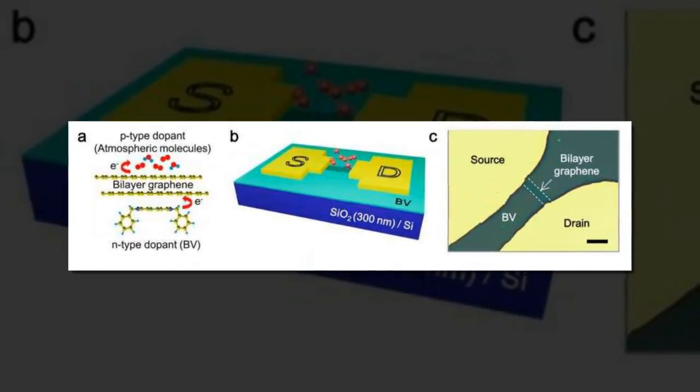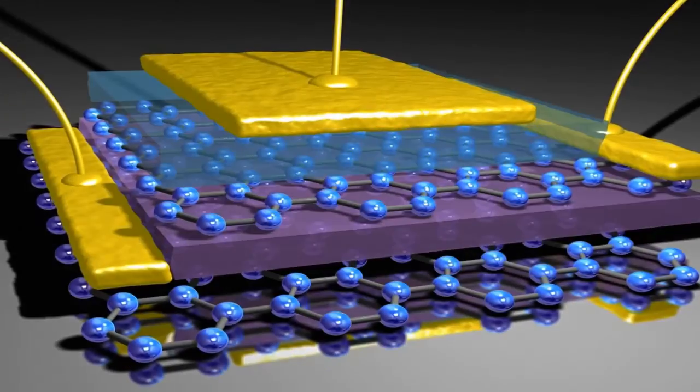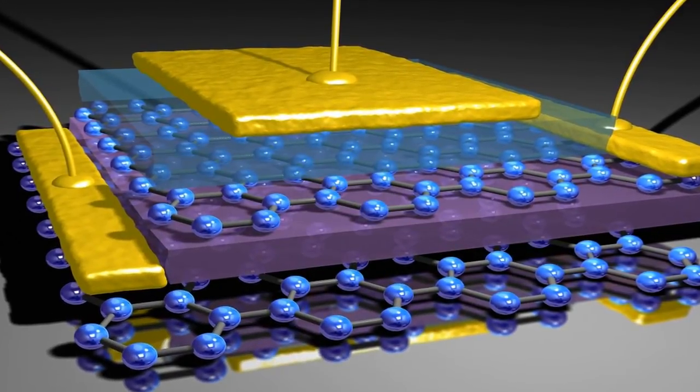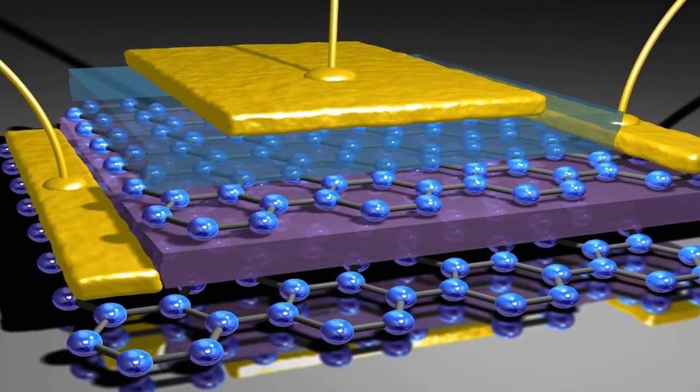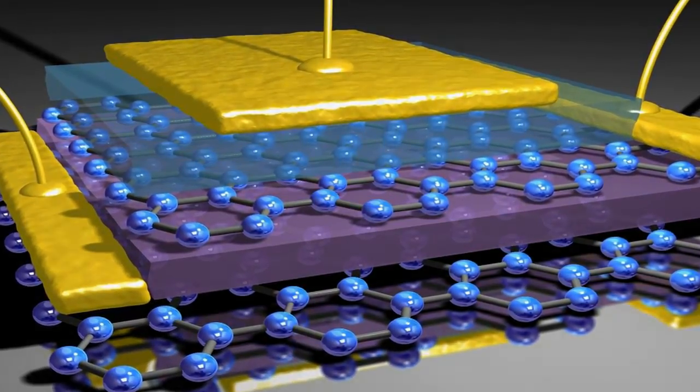Along with the highest on/off ratio for a device of its kind, 76.1 compared to 26, while maintaining graphene's naturally high electron mobility, 3,100 cm²/Vs.